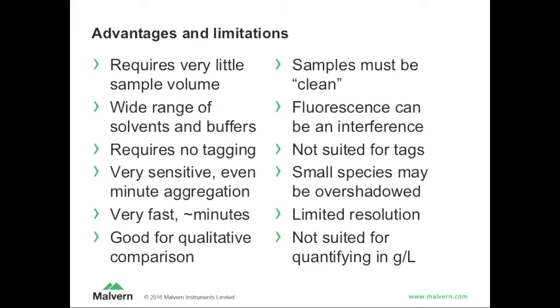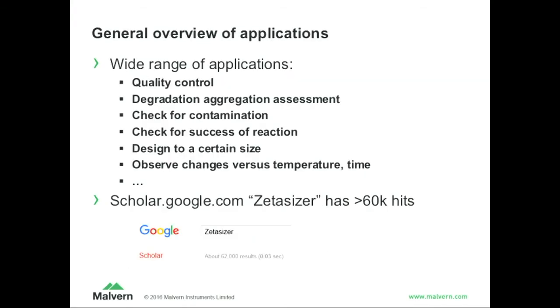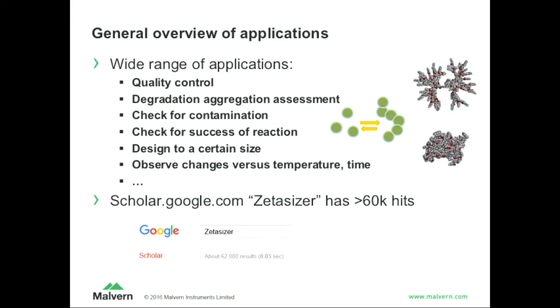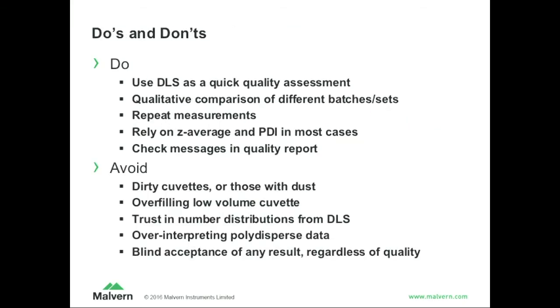What's nice about light scattering? Very little volume needed, wide range of conditions you can test, very sensitive, and it's just very fast. What's not so nice: it's label-free, which is positive, but you can't specifically tag certain parts of your distribution. So if you put nanoparticles into a whole big serum mess with all other cell fragments in there, forget it — it won't help you. There are a range of different applications people have used this for: quality control, looking at degradation, looking at equilibria, when particles form fibrils or monomers, and then maybe changing the pH or temperature so something expands or contracts. There's a ridiculously large number of publications out there using dynamic light scattering.